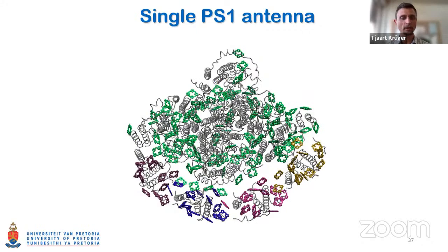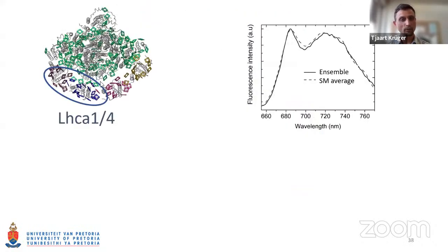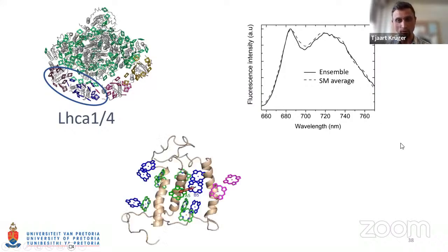So this is a model of the photosystem 1 antenna. Okay, then we took one component of it, actually two different components that are dimerized, so a dimer of them. Okay, and then started again by comparing the bulk spectrum with the single molecule average spectrum. And here you see the extremely broad redshifted band compared to the band at around 680 nanometers that was the case for LHC2. Okay, so this is now the equilibrium spectrum that we work with.